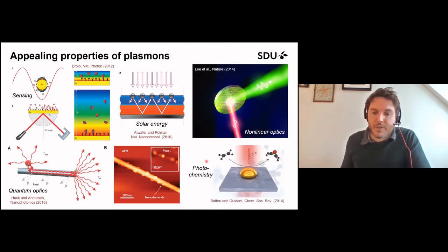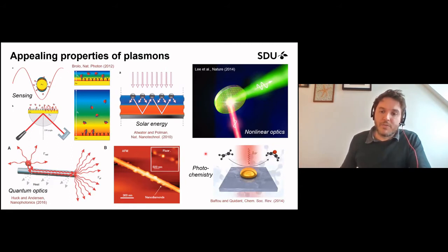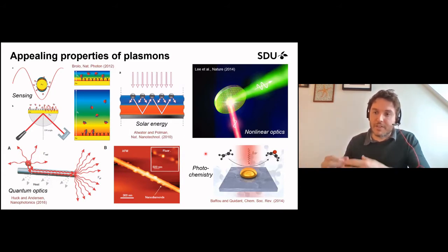And then there's also ways you can use the near field enhancement to control chemical reactions, actually, on very small length scales, either directly through optical changes or triggered by the heat that's created when you excite plasmons resonantly, right? So you're delivering a lot of energy to the electrons and they're oscillating. It actually causes them to heat up, and that heat can be diffusing out into the environment. And you can sort of have a nanoscale source of heat.